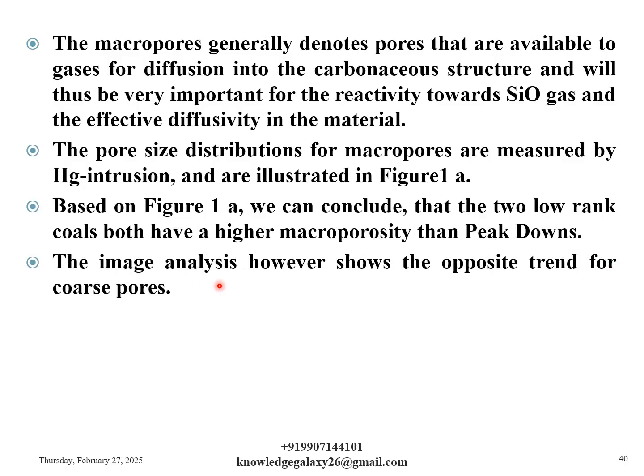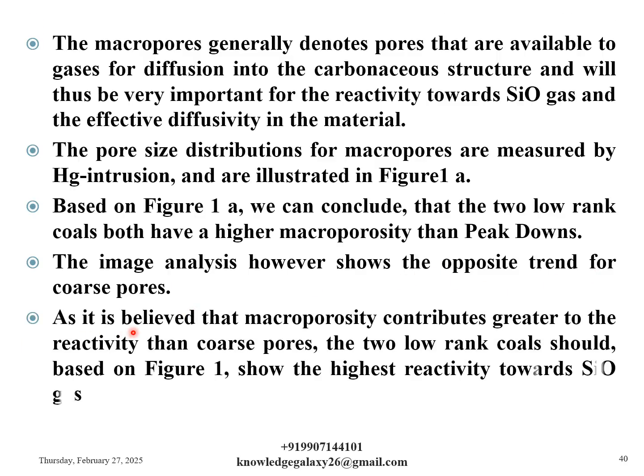The image analysis, however, shows the opposite trend for coarse pores, as it is believed that macroporosity contributes more to the reactivity than coarse pores. The two low-ranked coals should, based on figure 1, show the highest reactivity towards SiO gas.